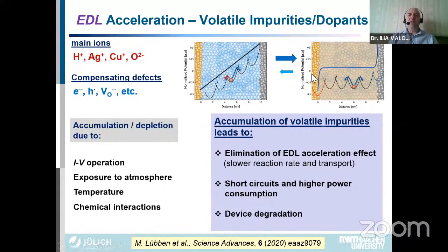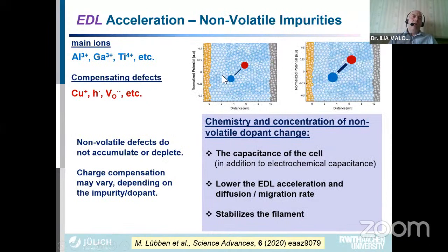Of course, with time, you can change from one situation to another, but it's much easier to incorporate more ions than to extract them all. So that's why the devices usually degrade with time, because you can never extract all the ions you have incorporated within them. What about impurities or dopants that you intentionally incorporate into your material? They have the advantage that they cannot move, they cannot be extracted, so their concentration remains constant. They cannot accumulate or deplete, and different ions may compensate their charge.